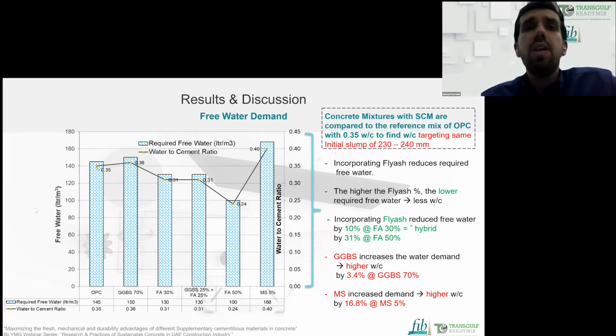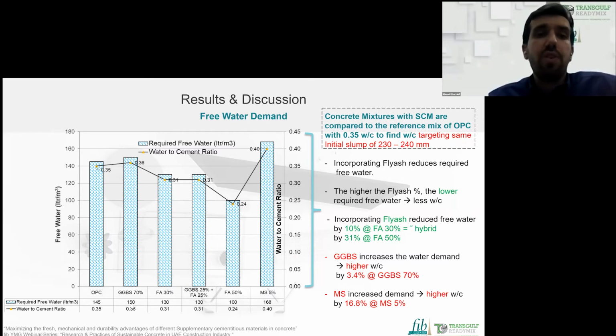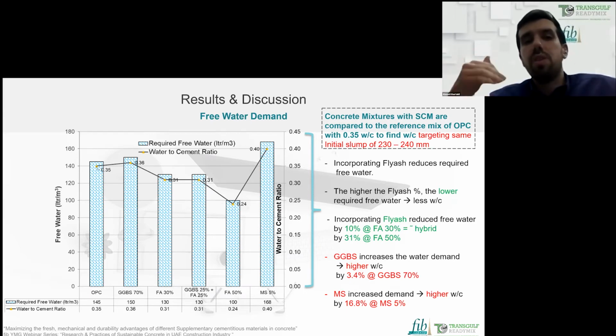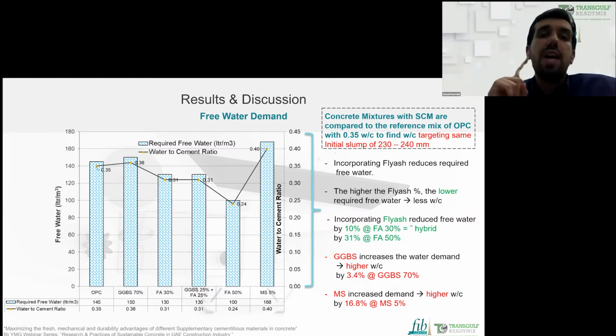And from the water demand test that was conducted, it can be noted from this figure, or looking into the values at the bottom as well, that at the same cement content, having a fixed admixture dosage based on the control mix, GGBS has a higher water demand. So it increases the water cement ratio, using the free water added to have the target initial slump, which was 150 compared to 145. While going to fly ash, when we have a 30% replacement with fly ash, it dropped to 130 liter, ending up with a water cement ratio of 0.31. And we all know that when the water cement ratio drops, definitely the durability of the concrete will be improved, and also the strength of the concrete will definitely be improved.